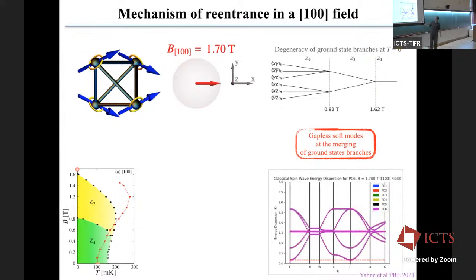But so the point is, around this point here, because you have merging of ground states, this merging of ground states creates soft modes. These soft modes mean that you have a higher entropy at this point, which means that this state here has a higher entropy than for lower field and for higher field. And because of that, this state is more stable at finite temperature, and that's why you have a reentrance phenomenon above this phase transition here.